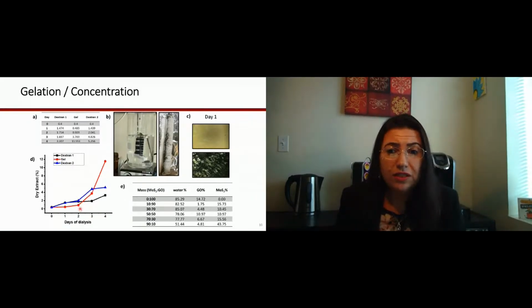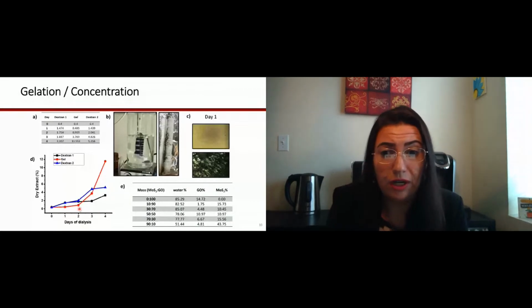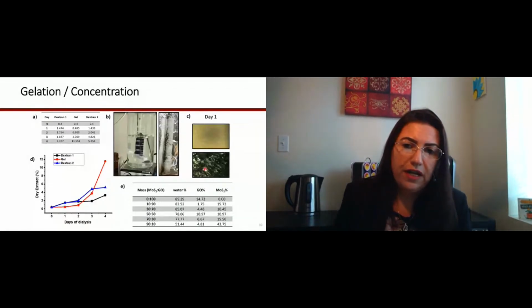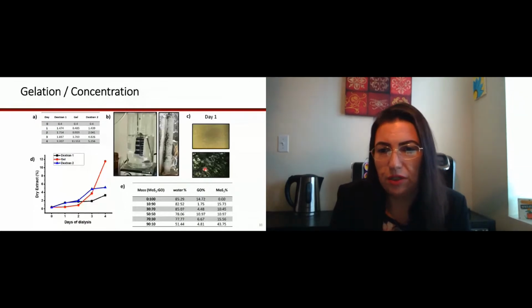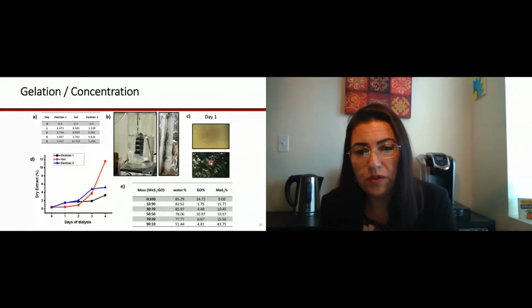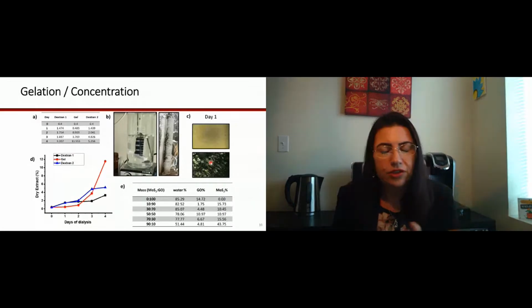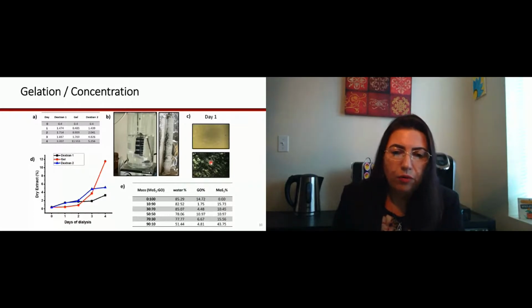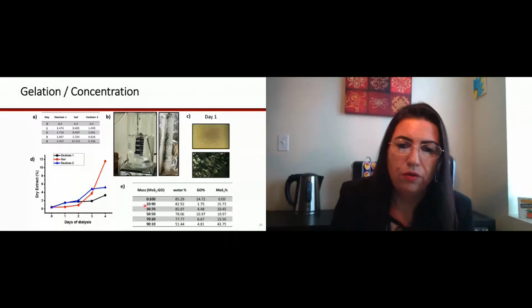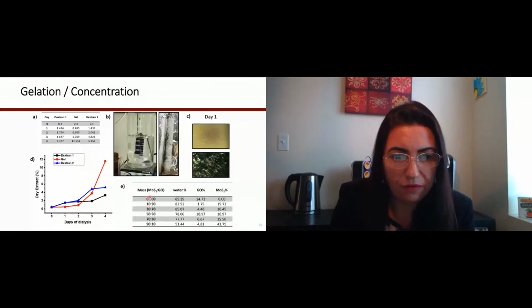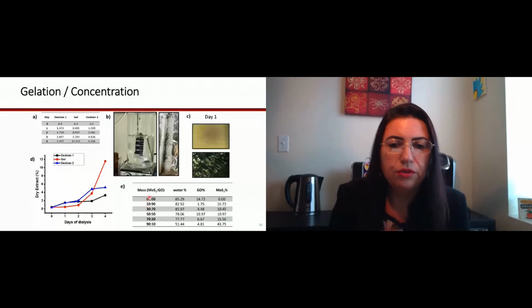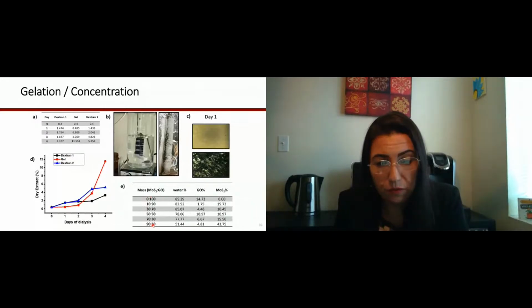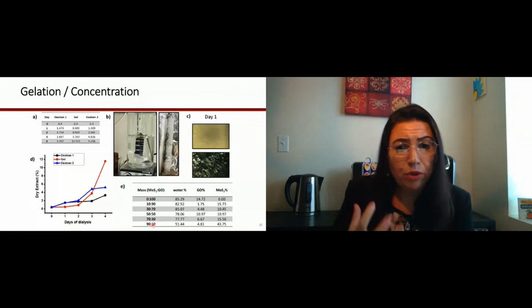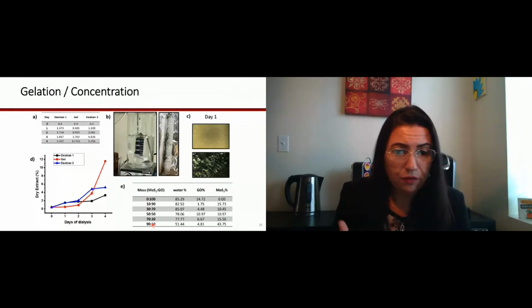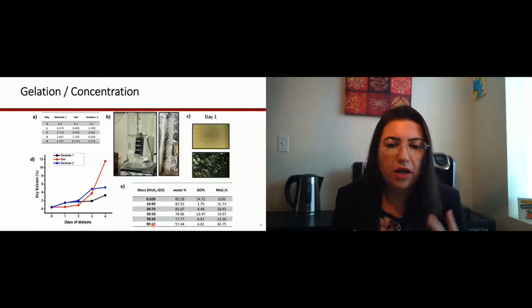So this was the first novelty, and from the first day we could already see the liquid crystal phase of graphene. So this is the same material, day one, and it really showed that the material was maintained properly from day one, and we were able to make different concentrations. So this is starting from just graphene and going from 90% to 10% of graphene, with the MoS2 used in powder.